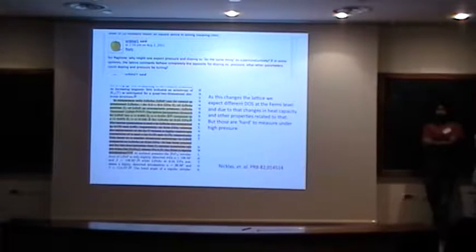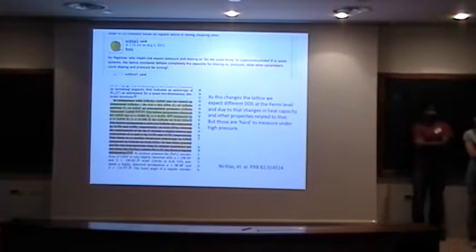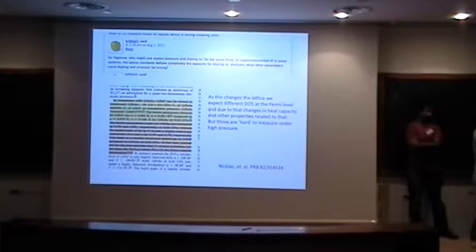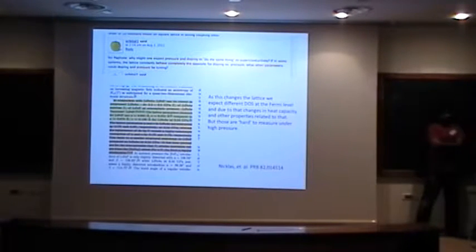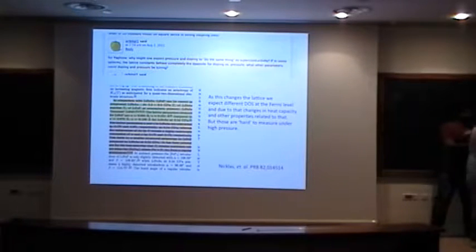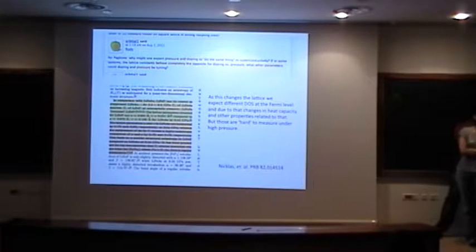Okay. Just a tiny comment on the 1111. If I remember correctly, there the difference between the arsenic and the phosphor is more in the height of the pnictogen atom over the plane than the lattice constant. So it may be a little bit delicate to transfer from one system to the other. There is a different parameter, which is the arsenic or phosphor height over the iron arsenic plane. And that changes actually the topology of the plane. Yeah, but that also changes in other materials.